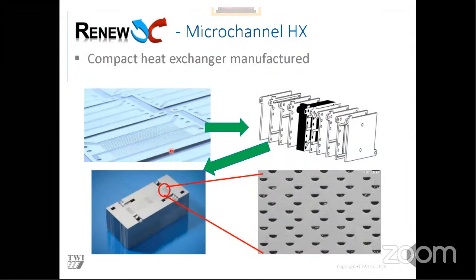And here are some, I've shown this image already. These images come from the RenewOC program. So we actually made some compact heat exchangers. And again, you have your photochemically etched shims. You stack them together, you diffusion bond them, and here are your channels. What I would say in this image, ignore the particles inside the channels. This is just where, when it's been cut, material is smeared over. So that's an effect of metallography. But yeah, there's your channels.